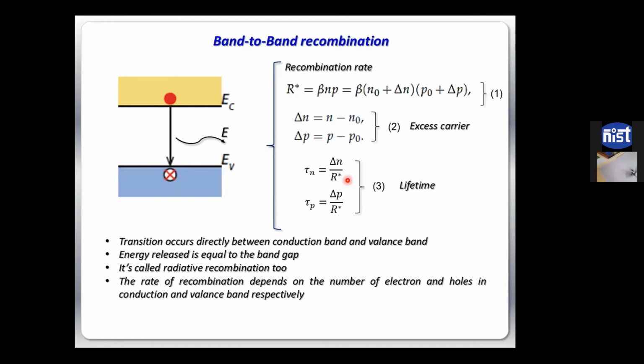Then the reverse process, recombination, is also easier for a direct band gap. Now for silicon, this is one advantage. The generation was a little tricky for the indirect band gap, and this recombination is also a little tricky for the semiconductor. That is why this semiconductor has almost a microsecond of lifetime, which is very favorable for solar applications, because most of the direct band gap materials, if you see, have lifetimes in the nanosecond range, right?